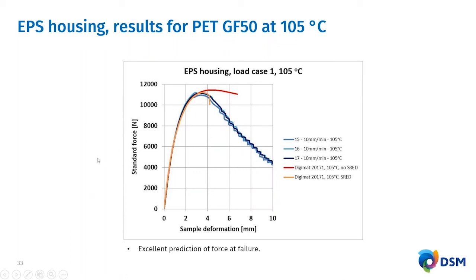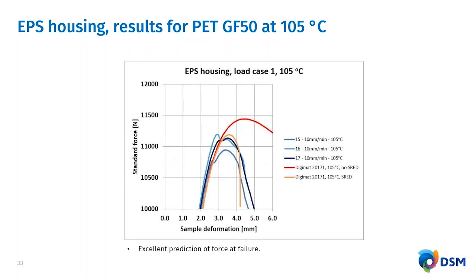So here's some additional results with the EPS housing. This was at the 105°C test temperature for this particular load case. The blue curves, 15, 16, 17, represent the experiment or the actual test, and the red and orange curves represent the predictions. And as you can see, there's a fair amount of agreement, providing just excellent prediction of the force at failure. We zoom in on the top part of the curve. That's what that looks like.